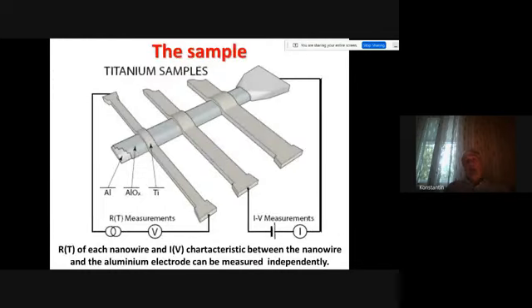So now we decided to test the same structures, titanium nanostructures, where we can measure the resistance of each nanostructure, for example, as function of temperature. But each of the titanium nanostructure overlaps with a massive superconductor aluminum through a tunnel barrier. So within the same structure, we can measure both the integral property, let's say resistance of nanowire, and also its density of states due to tunneling between superconductor 1 and superconductor 2 through a thin insulating layer. And these are local parameters because they characterize the density of states and superconducting order parameter just within the interception region, which is just few hundreds of square nanometers.